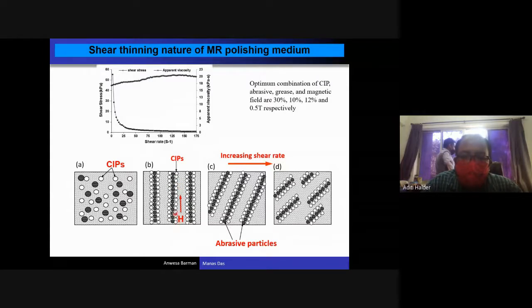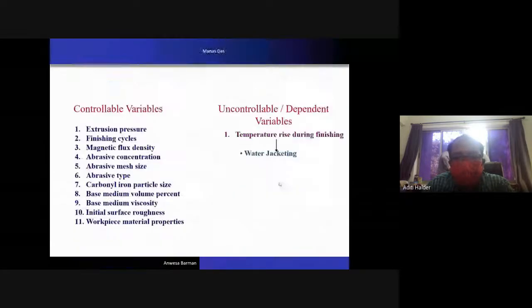Now when you apply a certain amount of shear rate here, this chain structure breaks. When you use a higher shear rate, the chains initially bend, but after that they break and do not get time to realign again. So there is permanent chain structure breakage, and only then will the MR fluid flow. That's why this MR fluid is called a shear thinning fluid.